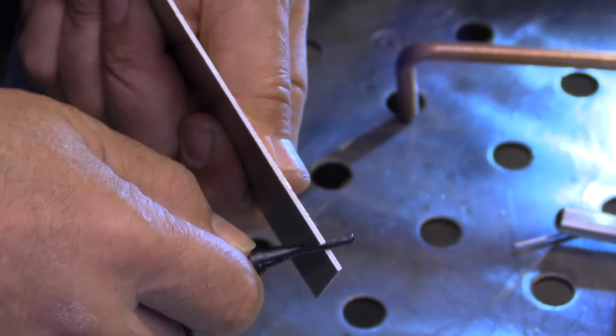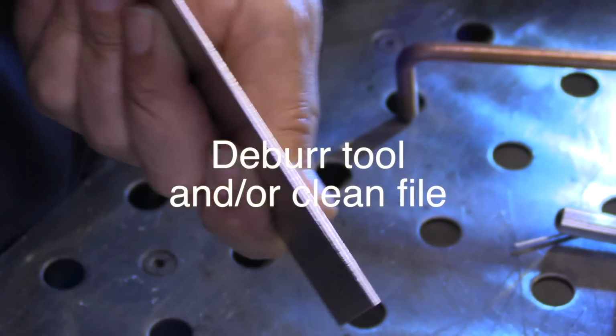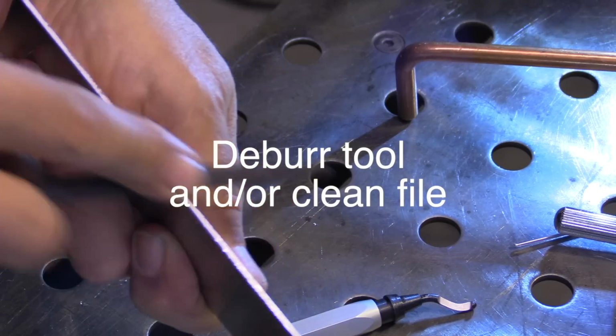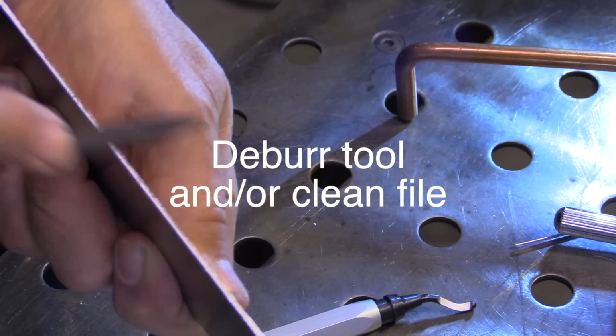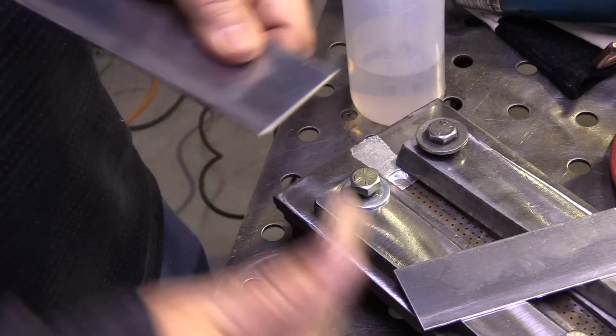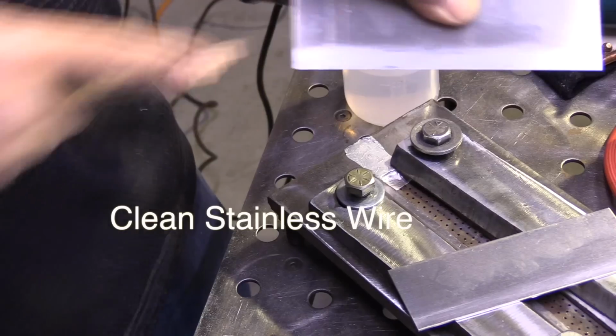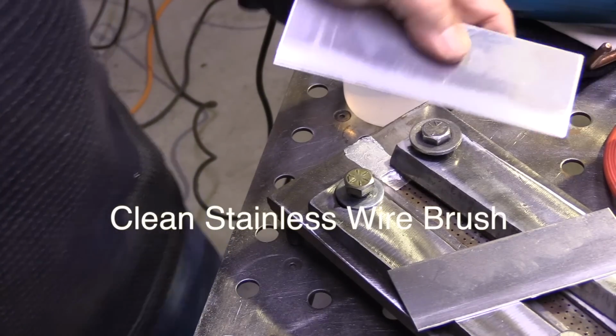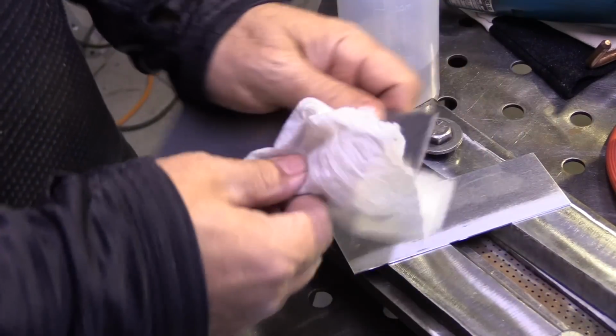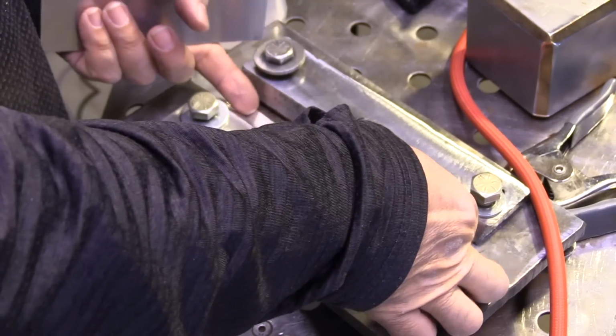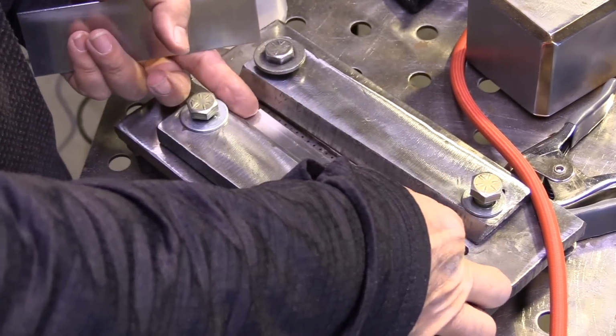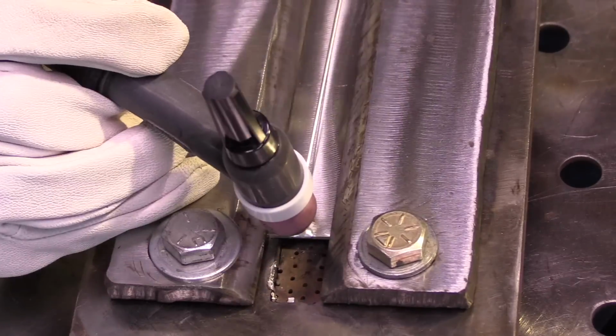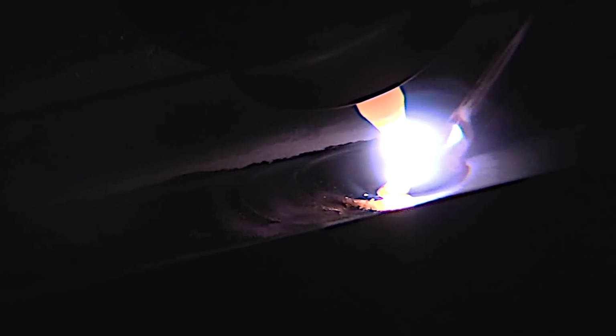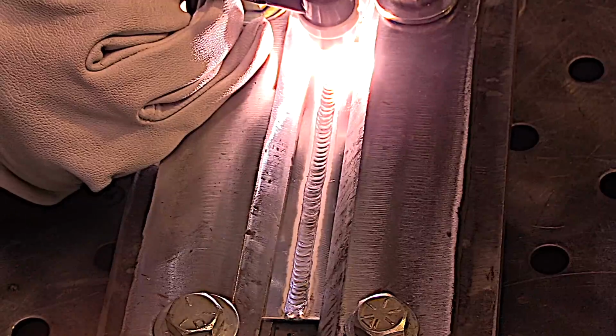There could be lots of oxides and oil trapped in that, so using a deburr tool or a clean dedicated file is one of the things that makes the most difference on X-ray results. Of course, it helps to clean it with a wire brush. It helps to clean it with acetone. It also helps to use a slightly slower travel speed to give the bead time to outgas any impurities that might be left over. In this case, just pausing for a half a second or so after dabbing filler wire can help.